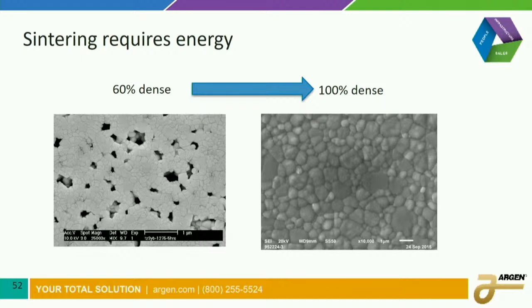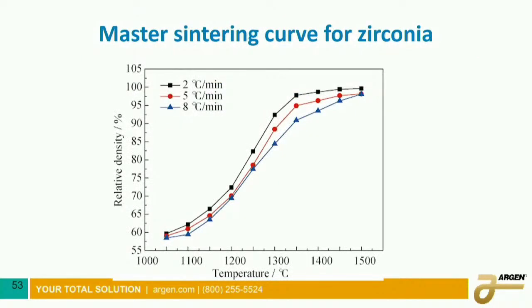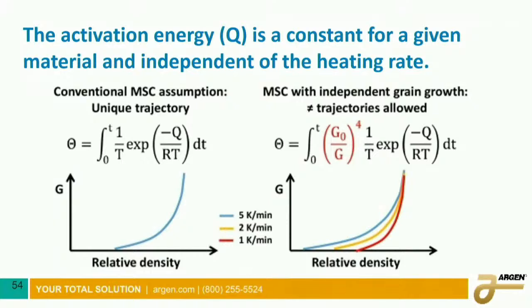Now, traditionally, if you tried to do this with some devices, you could find something called a master sintering curve, and this is what's done on every material that we develop. You change the rate, and you start and you stop, and you're trying to find a curve that's going to work for all different cases. And when you find that, now you calculate what the activation energy is. Now, if you use conventional heating, you only wind up with one curve. So you have to follow a fairly conservative sintering cycle, like 4 hours for, say, a 3-unit bridge or single units. However, if you could tap into that extra energy, now we could go a little faster, and we could get denser faster, and that's what we're trying to do.